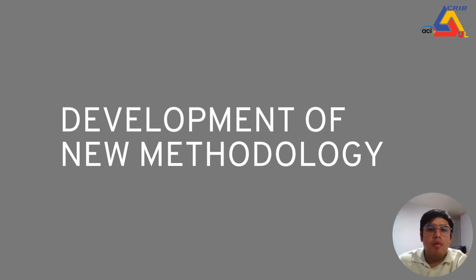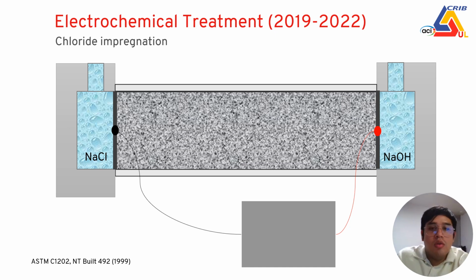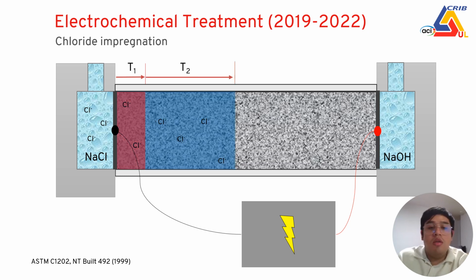Now I'm going to talk about this methodology, how I developed it. This methodology starts with the chloride impregnation of the electrochemical treatment. It's when we put a concrete specimen in an electromigration cell, and with the help of the voltage we generate the electrolysis of water, and chloride will be free in the system. This chloride will try to migrate to the positive part of the electromigration cell over time. So we just need to wait.